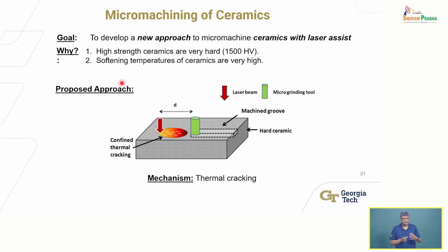You can actually generate sufficiently high, let's say, thermal radial stresses or circumferential stresses, depending on which mode of failure is easier to promote in the ceramic. You can actually produce cracks and weaken the material, as I described earlier on. That's the basic idea. So thermal cracking as opposed to softening, okay? And then I can still use a grinding tool, but now the grinding tool is simply removing already weakened material and cracked material. So it should require less forces, the wear on the diamond wheel should be less, and so on and so forth, right?